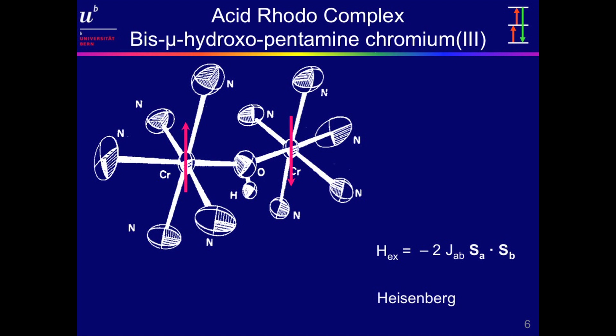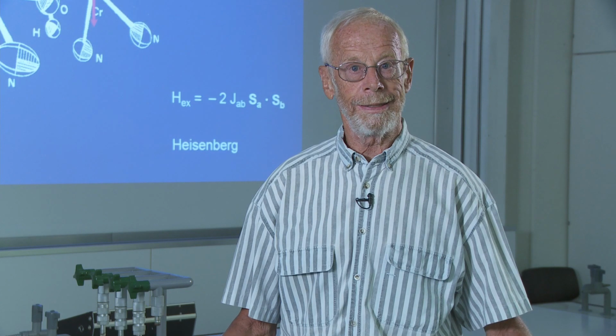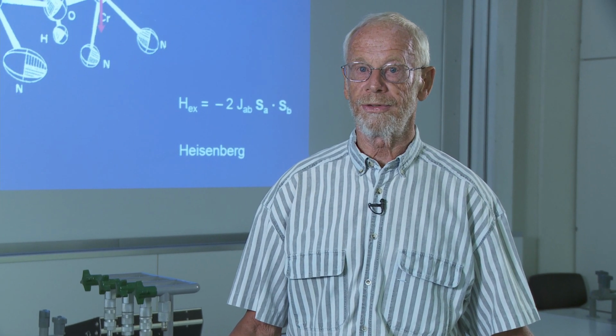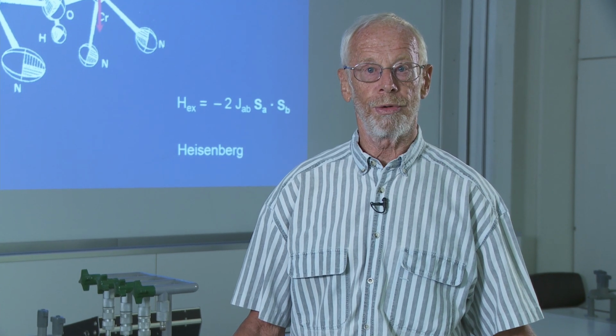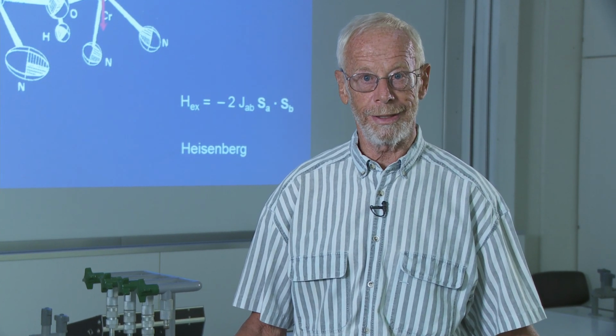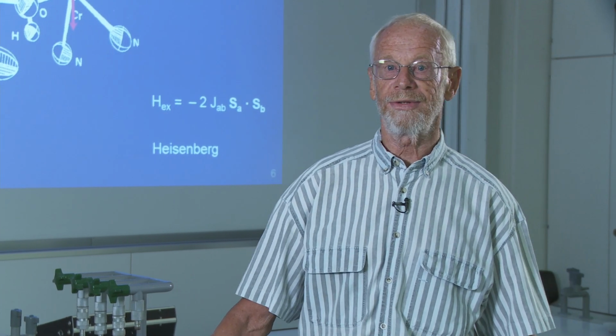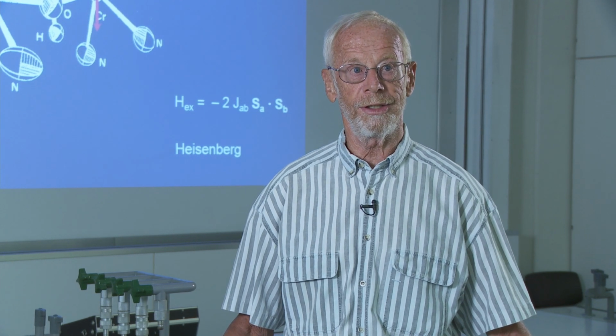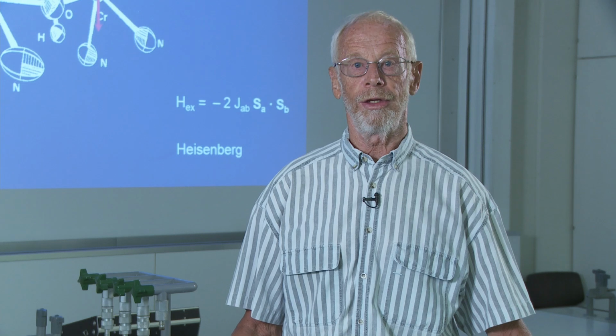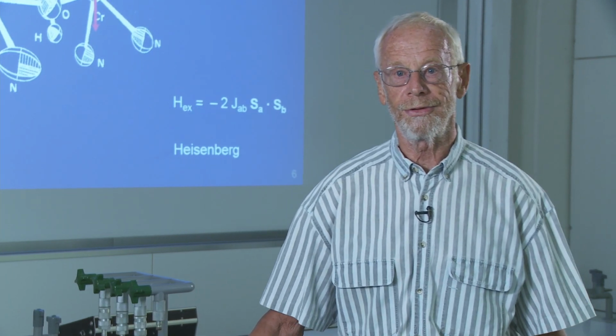And this hydroxo bridge causes the chromiums to interact antiferromagnetically because the d orbitals of chromium overlap with the s and p orbitals on the oxygen. This is called exchange interaction, can be represented by a Heisenberg Hamiltonian, and this interaction is responsible for phenomena such as ferromagnetism or antiferromagnetism in oxides and halides. And that's why in those days physicists and magnetochemists were very interested in studying these simple dimeric units to get insight into the nature of these couplings.